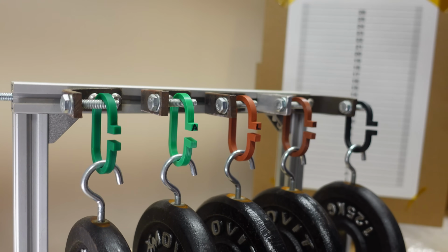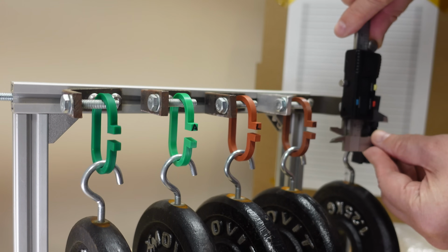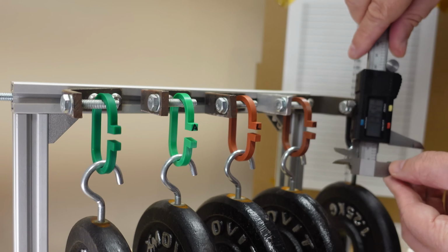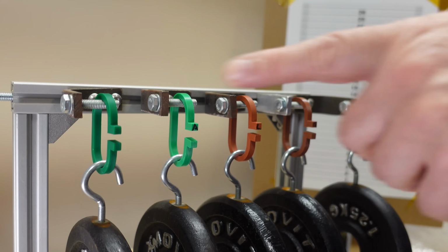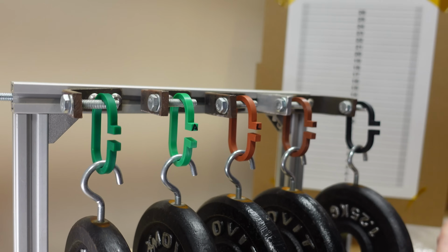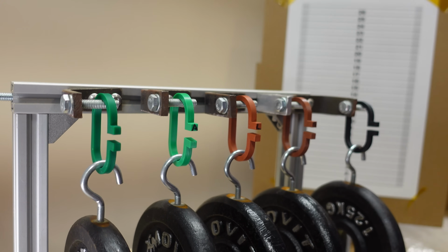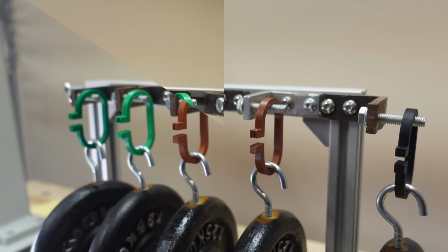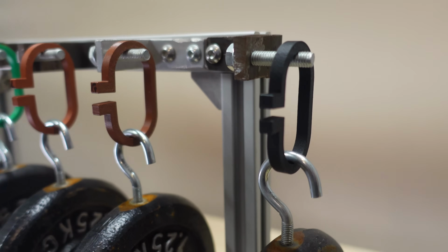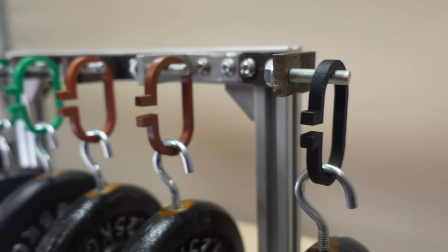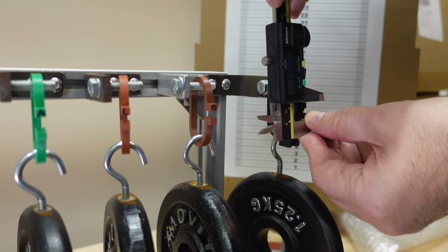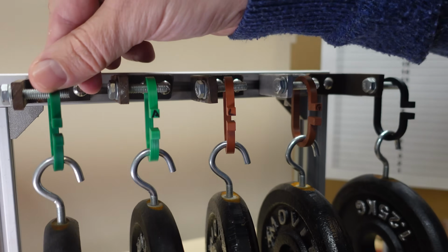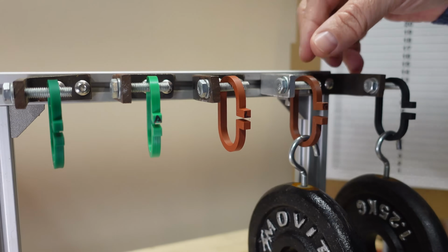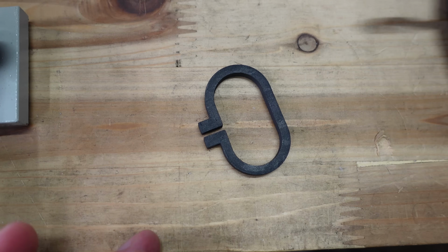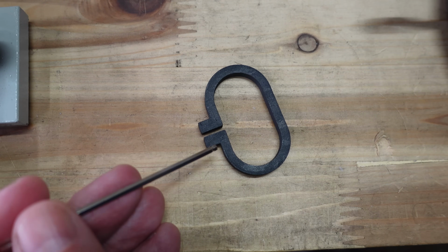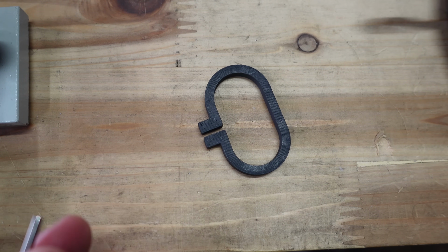Very minimal deformation. I am measuring the distance between two reference surfaces, 13.54. From all these materials, these have the smallest deformation, but we will see what will happen after 5 days. But I will measure them every day. This is the last 5th day, and the smallest deformation I can see on this carbon fiber ASA. 13.64. And now let's remove all loads. I already measured it. Immediately after I removed the load, it got back the original shape almost without any permanent deformation.